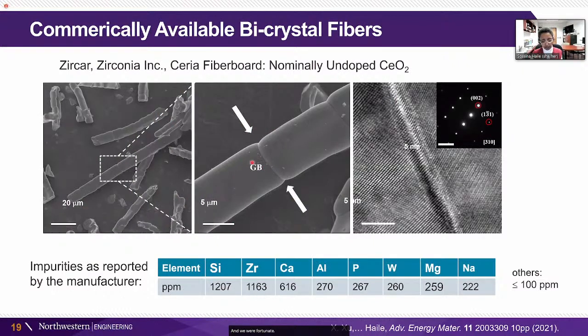And we were fortunate that we could get some commercial nominally undoped Ceria fibers that have the optimal configuration, optimal geometry for us to be able to have these grain boundaries that are normal to the length of the fiber. We have these nominal impurity concentrations. These are, of course, much higher than the impurities in our high purity sample. This is what was given to us from the manufacturer. And we can see that the interface here is certainly, despite the presence of impurities, a sharp interface with no impurity phase per se. It's just impurity concentrations.